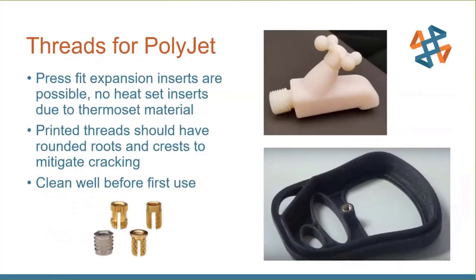For PolyJet threads, you don't want to use heated inserts because PolyJet doesn't melt back to a liquid when heated — so no heat-set inserts. You can print threads in there; it's always good to chase them afterward, and you can put wire coil inserts or key inserts if you need to go in and out many times.